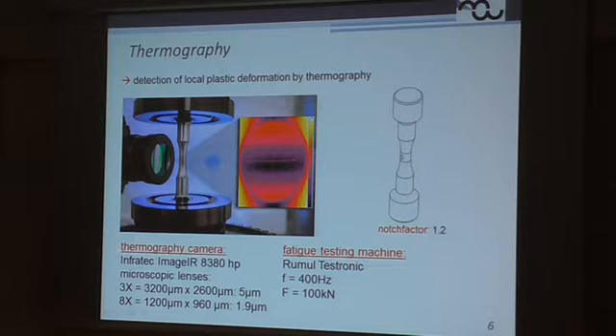We are using therefore a thermographic camera from the brand InfraTec from Germany, and this picture here shows the magnification. So this is 2.6 millimeters and 3.2 millimeters, which results in a resolution of 5 micron for 1 pixel. And this camera is adapted to the Rumul Testronic machine.